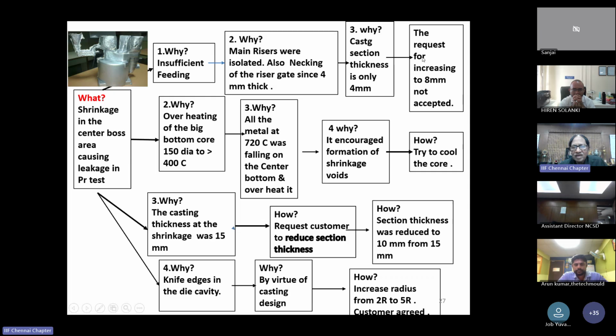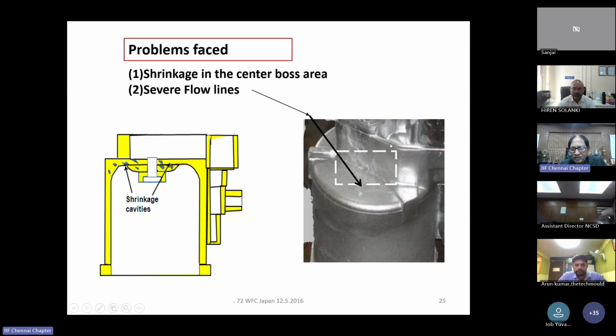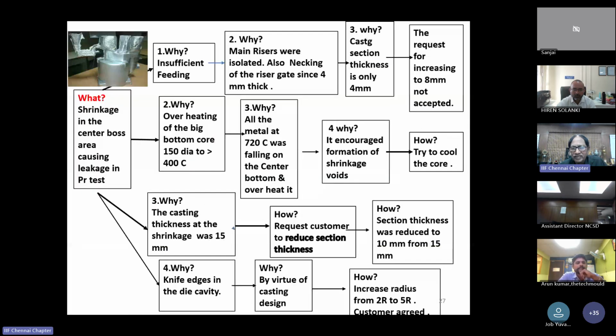We tried to ask the customer whether we can reduce the thickness there. The customer was kind enough to reduce it to some extent, which I will explain. Then the second cause is overheating of the bottom core. Why? The metal which is at 720 degrees is fully falling on the top of this portion and getting overheated, unlike the side gating.